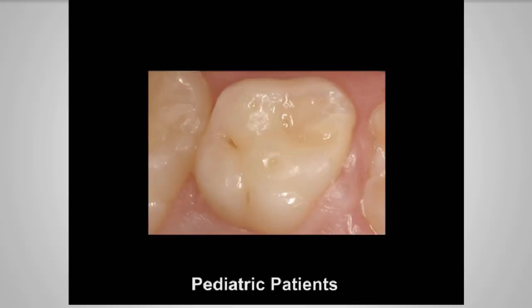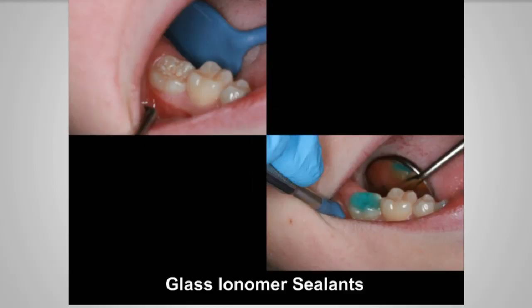And my experience has been that when you use the pure glass ionomer, you have less postoperative sensitivity, though we don't get that much with kids anyway, but they seem to stay in the best. I have better retention. That's my personal feeling. I have better retention with glass ionomer than I do with resin modified, and I have better retention than I do with amalgam or with composite.